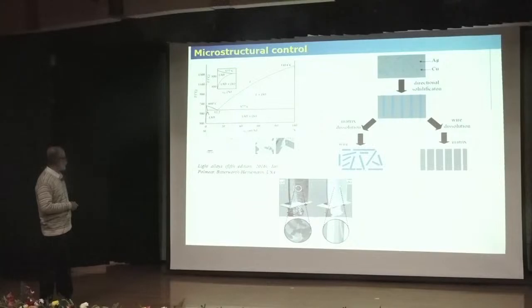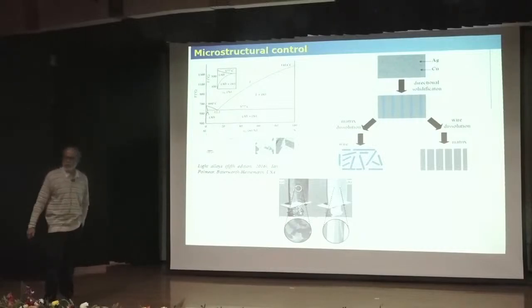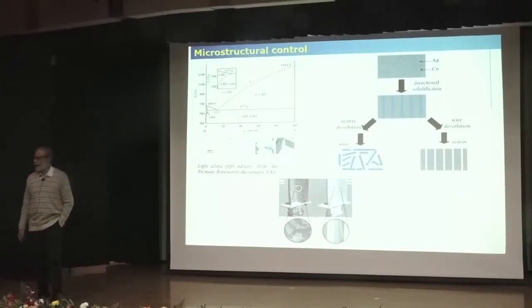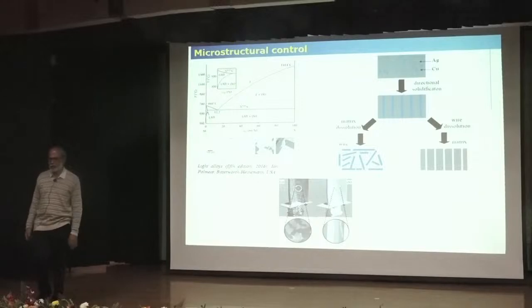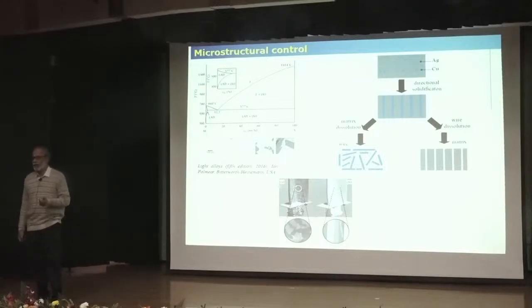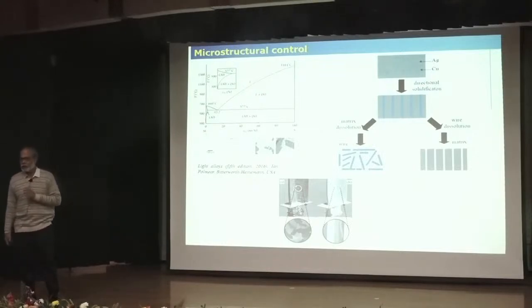So if you go through silicon content, the microstructure will vary like this. The primary phase, you will get coarser and coarser primary phase, that is silicon, which is very brittle. So people wanted to get rid of this coarse, brittle silicon in the aluminum matrix, and for that they adopted some grain refiner like titanium boride, or some modifier like strontium, antimony, cerium, which modify the shape of the eutectic, right? So that's how they could engineer the microstructure.